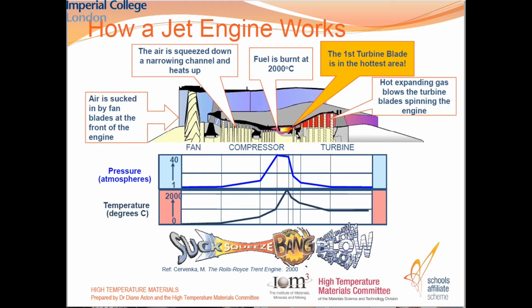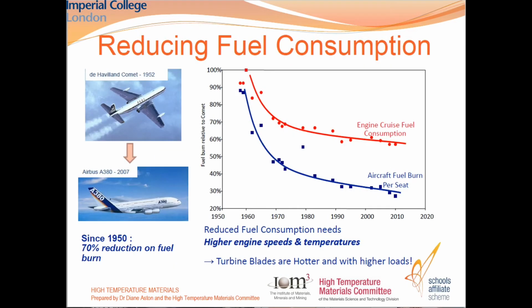These blades, especially the first line of blades, have to withstand really high temperature. Not quite 2,000 degrees. By the time the air gets to them, it tends to have cooled down, but maybe about 1,600. And they need to withstand up to 40 atmospheres, which is very, very difficult operating conditions. To reduce fuel consumption, we generally look for better speed in plane engines, and that tends to push the engines to their extremes. They are getting hotter and hotter all the time to try and maximize efficiency, and that puts a huge strain on the material and on their properties. So new materials need to be developed regularly to fulfill the needs of the air engine market.